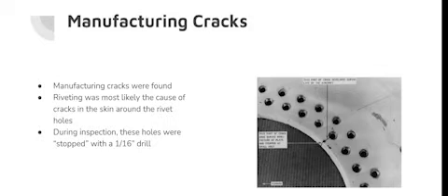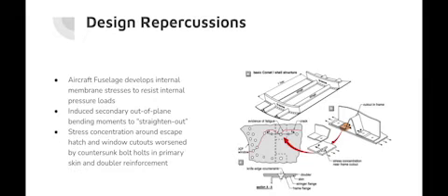The punch rivet construction technique had worsened the Comet's structural fatigue problems. Its aircraft windows had been specifically engineered to be glued and riveted, not with the technique of punch riveting. The imperfect nature of the hole created by punch riveting could cause fatigue cracks to start developing around the rivet, and develop they did. Additionally, circular cylindrical structures such as the fuselage developed internal membrane stresses that were constant throughout